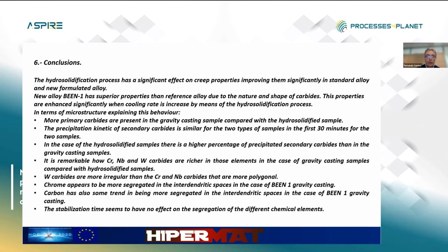Also, it's remarkable how the different carbides are richer in the main alloying elements in the case of gravity casting compared with hydrosolidified samples. We can also see how tungsten carbides are more irregular, while chrome and niobium carbides are more polygonal, that chrome and carbon are more segregated in the case of gravity casting, and that the stabilization time has no effect on segregation of the different chemical elements.